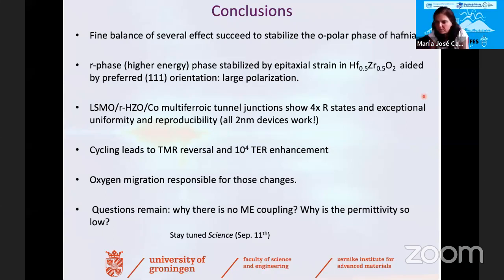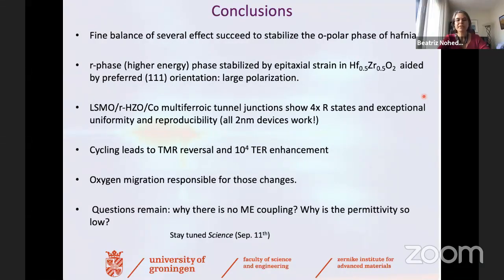Okay, there is another question by Philippe Sandiumenge. Is there any knowledge on the stability of these metastable polar phases in the presence of oxygen vacancies? Yeah, that's a very good question. There are a couple of papers coming from my group about this, and I think others have also investigated that. I don't dare to say much about the orthorhombic phase, but for the stabilization of the rhombohedral phase, we believe that oxygen vacancies are important. It may have to do with the volume changes that are needed. So we do think that the rhombohedral phase is stabilized thanks to oxygen vacancies in the material.